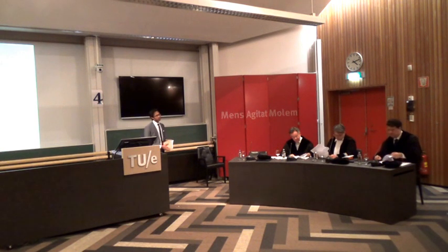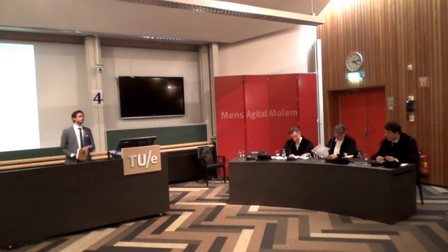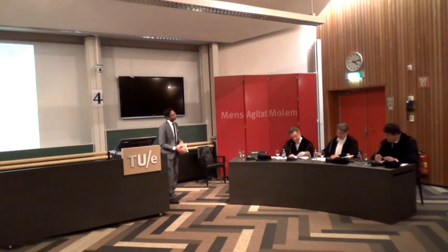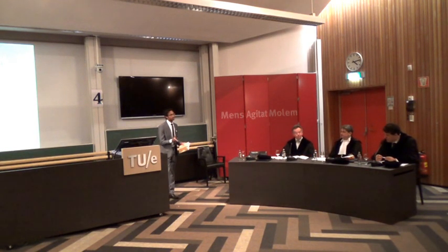But to explain more about that, in case of extrusion, people believe that extrusion would reduce the aspect ratio of the carbon nanotubes because of the shear involved. It cuts the carbon nanotube. Maybe that could be one of the reasons that I'm getting the higher electrical percolation. But still, during the extrusion process, I'm using a very low shear rate, and at the same time, I also measure the aspect ratio before and after extrusion. It is almost similar. So I believe the aspect ratio is not influencing my curve, but in general, using a high aspect ratio will give you better conductivity, low contact resistance, and all these.